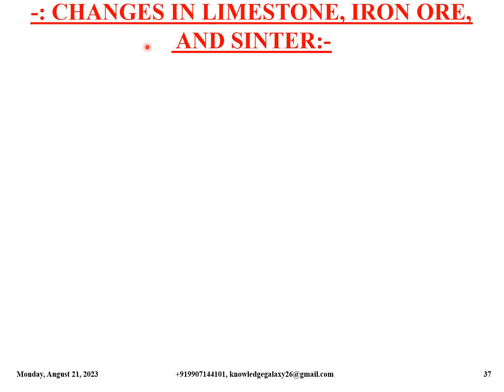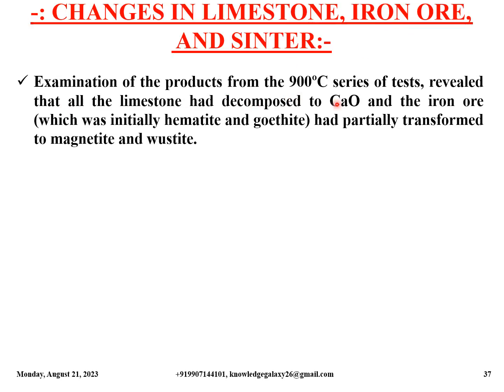Now let us discuss the changes in limestone, iron ore and sinter. Examination of the products from the 900 degree Celsius series of tests revealed that all the limestone had decomposed to CaO and the iron ore, which was initially hematite and goethite, had partially transformed to magnetite and wustite.